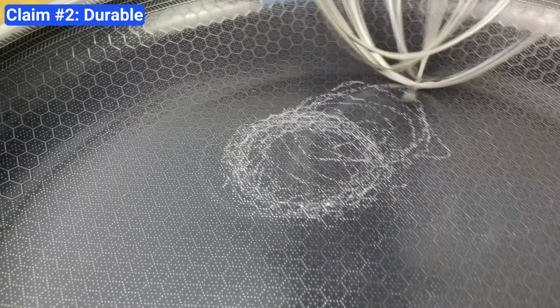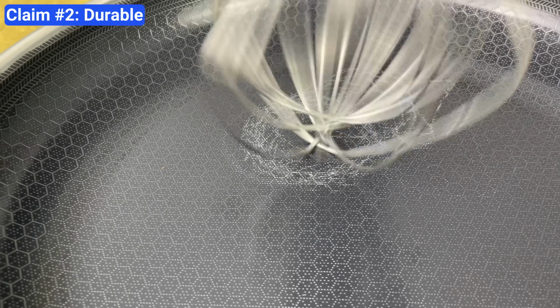To put those results in context, I ran the same tests on a Teflon-coated pan, a ceramic nonstick pan, and a hex-clad pan, and all 3 of those ended up with visible scratches or coating damage after 1 or more of the tests.